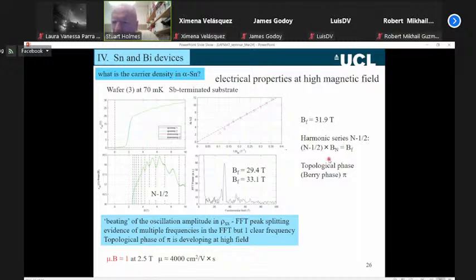But it turns out this n minus a half, this is a phase, an extra phase coming in. So we've got this extra phase coming into the oscillations due to the topology in the system. So we have this topological phase coming into the system. So that tells us straight away that it's not a bulk tin band. It's a band coming from this topological state in the surface region. So it was quite an interesting result to get this. We were quite lucky to get this result.